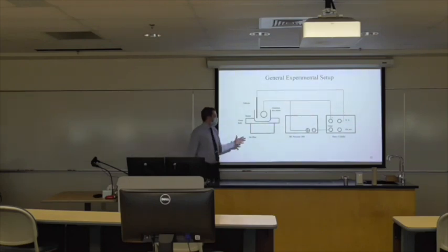So we have a beaker on a stir plate with a water bath in case any of the processes were significantly exothermic and might raise the temperature. These processes tend to be temperature dependent, so trying to keep the temperature as even as possible is ideal, especially at room temperature, where you don't want to get far from room temperature.